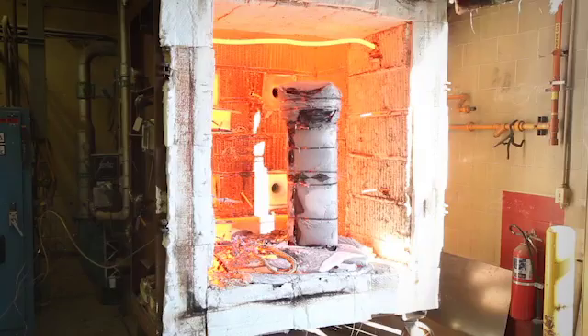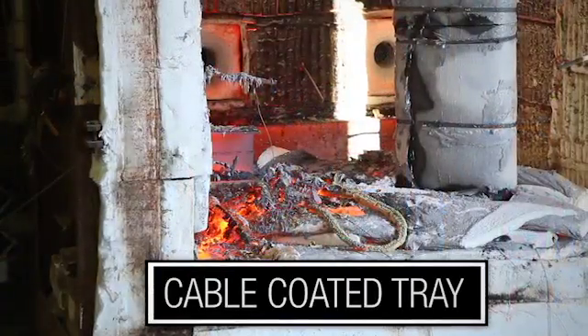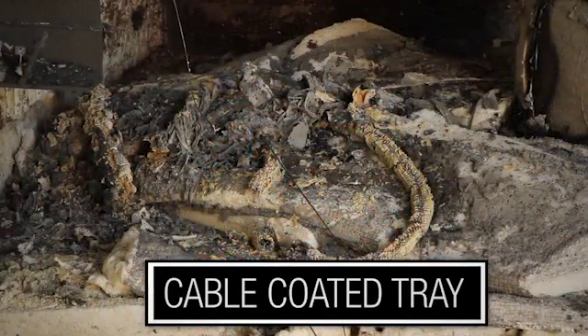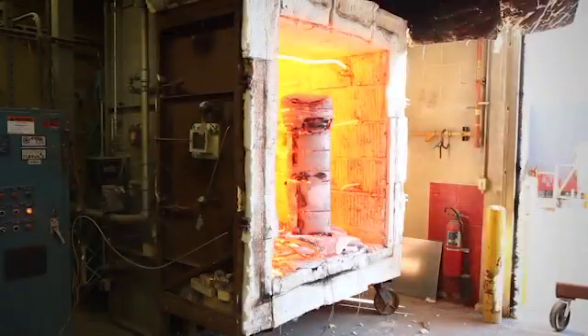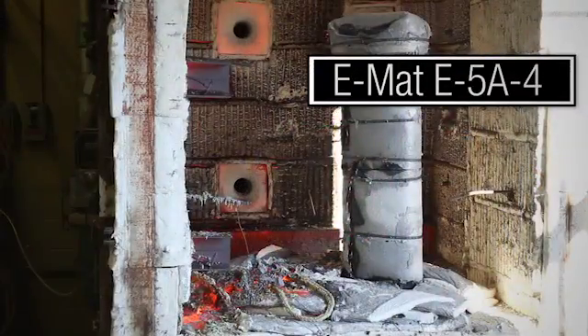Just minutes into the test, the cables protected with the coating have failed the temperature limit and then continue to fail catastrophically. First, the cable's electrical insulation burns away, the copper conductors unravel and melt, and the tray collapses onto the floor of the furnace. In contrast, the EMAT-protected tray has maintained the cable temperatures at acceptable levels. The tray's structural integrity is intact, and the electrical insulation jacket is still intact.